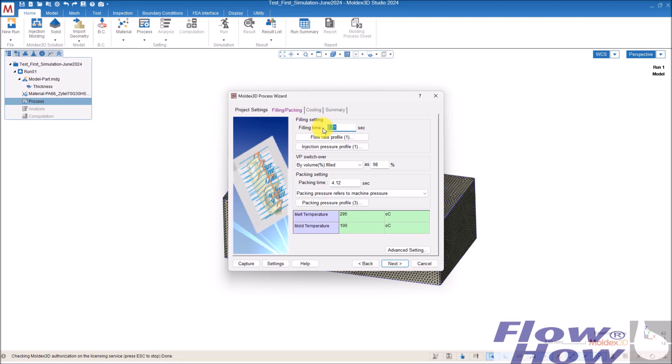Of course I have a bit knowledge about how it should be. But very small parts like earplugs or something like that, not below 0.3 of a second, because it's really not possible for a real injection machine to do that. But 0.3 to 0.8 of a second is normal. And for medium parts like lids for a small food container or something, around 0.8 to 2. And bigger parts like some cover to electronics or something is 2 and below, and over that. But this also depends a lot on the wall thickness. But in this case I just give one second.